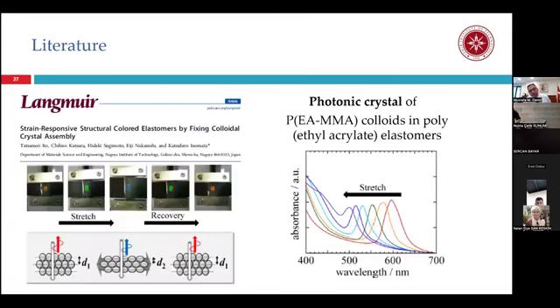One piece of work from literature, on the very left-hand side, you see a picture. So there is one transparent elastic polymer, and one region is coated with colloidal crystal, shown by orange. If you stretch, it turns into yellow. If you stretch more, you have seen blue shift, it turns into blue. If you release, then you have the recovery of the material and recovery of the color, because the interparticle distance changes, it turns into yellow, then it turns into the original orange color.